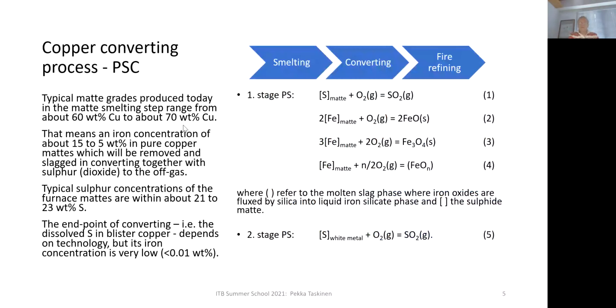And in normal cases, in the current copper industry in the world, they are producing furnace matte from flash melting or other smelting furnaces, which contains from 60 to 70% copper. That means that there is about 15% iron in 60% matte grade and about 5% iron in 70% matte grade. And this iron, independently of where we start from, will be removed in the first step of converting, and that first step